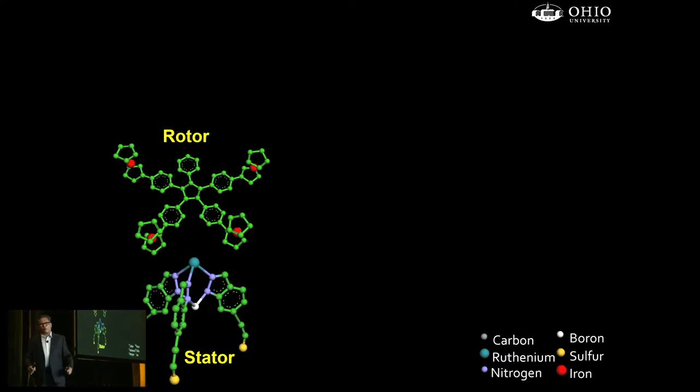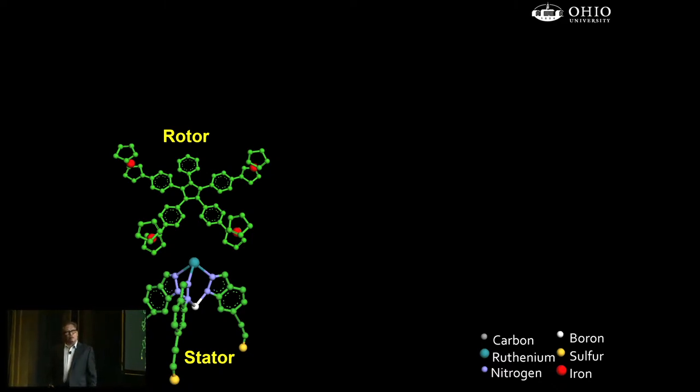We call it the molecular tripod, and when we deposit these molecular motors, they have to stick correctly, that means positioned upright. So the legs have to stick. We put sulfur groups here in order to stick on the gold substrate that we are going to use. If we want to use silicon, we can change that to oxygen, for example. So this is very nice. And we have the rotator, or rotor, which has 5 arms, 5 blades. On purpose, we truncated one, so that because of the asymmetry, we know when it rotates. At the end, we have the ferrocene group, which contains iron atoms.